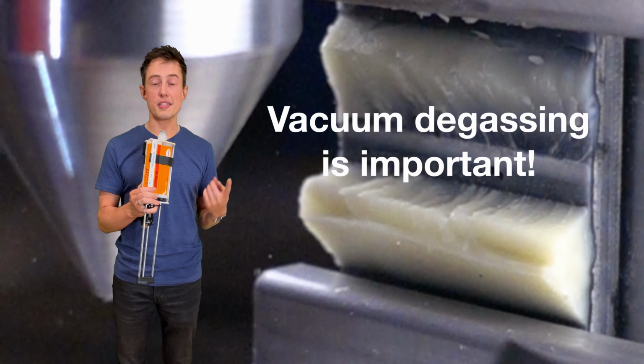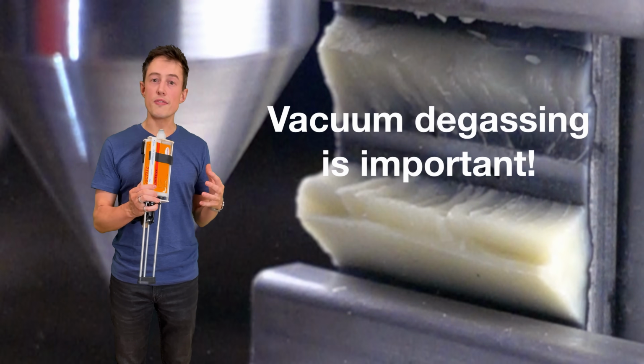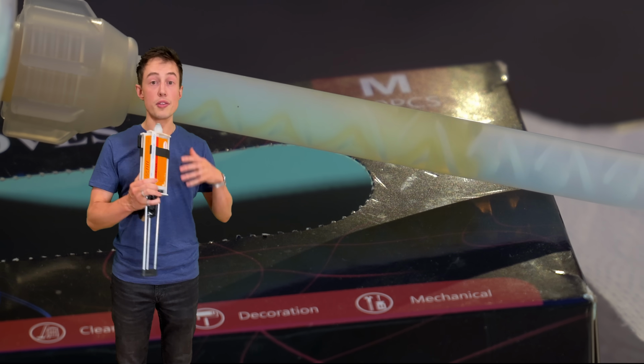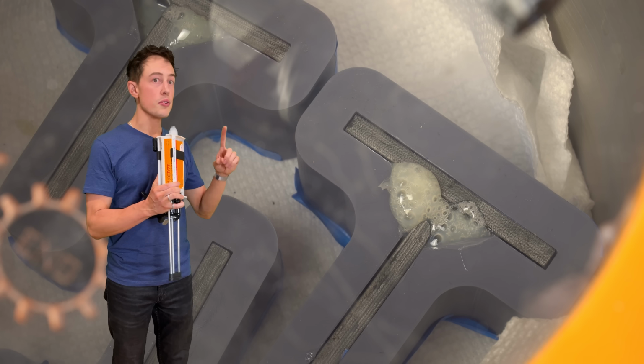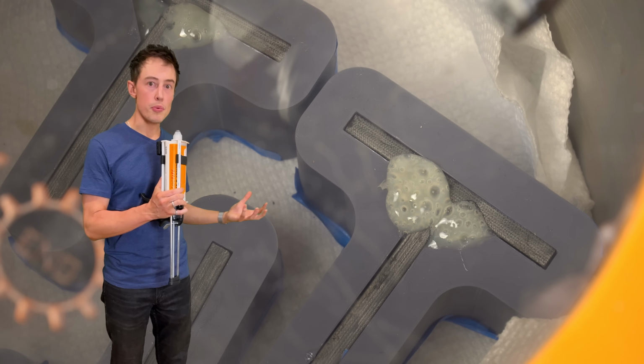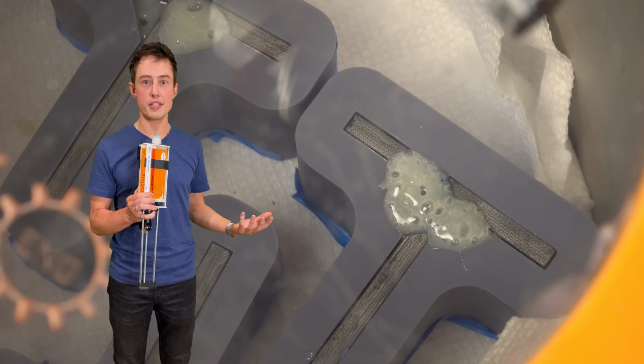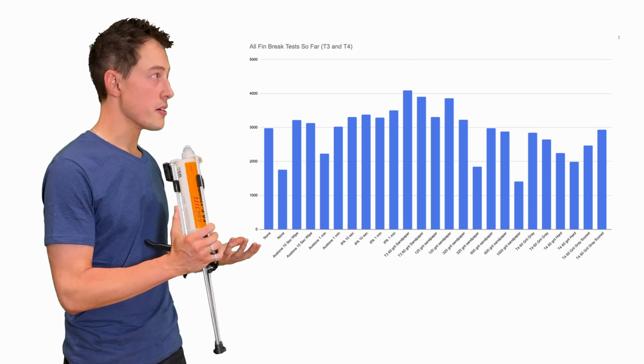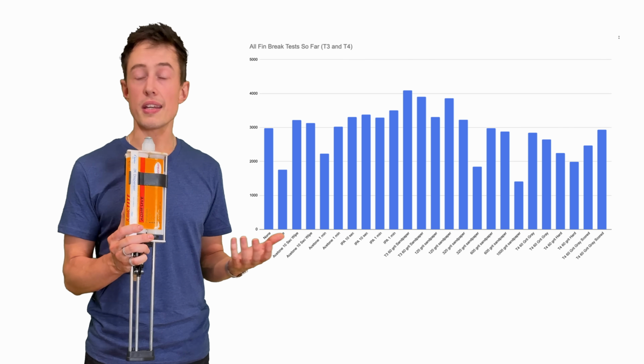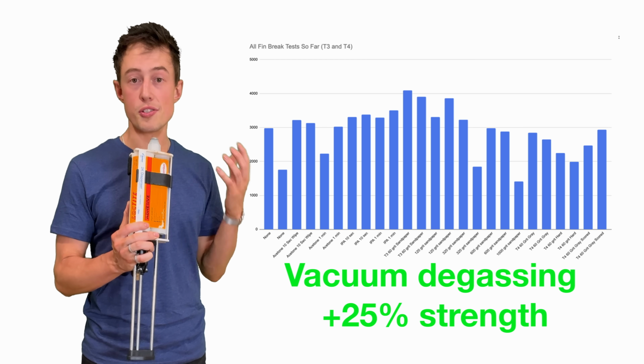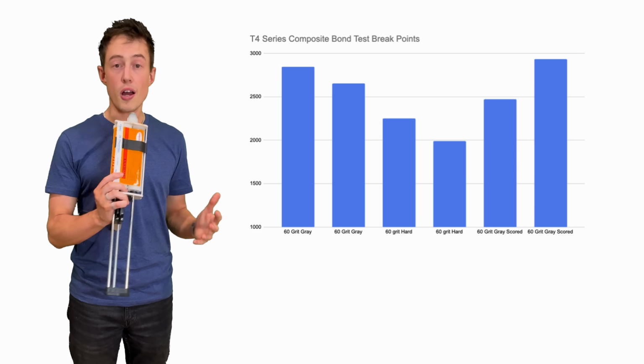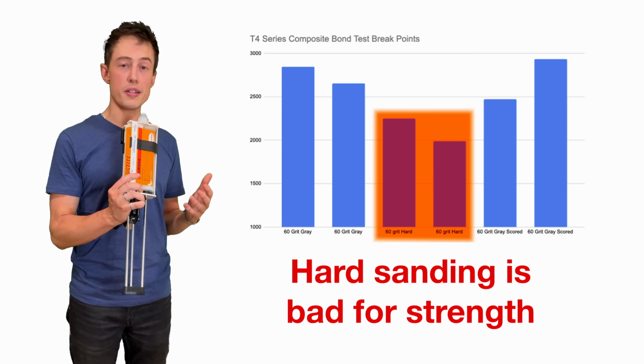First, vacuum degassing is important. I think that even if the mix nozzle is doing a good job and there aren't many air pockets, we're still getting further mixing when those bubbles come out through the vacuum degas process. If I had to guess, using my data alone, it looks like vacuum degassing can add as much as 25% strength into the epoxy. Further, hard sanding seems like it can reduce the strength of the bond.